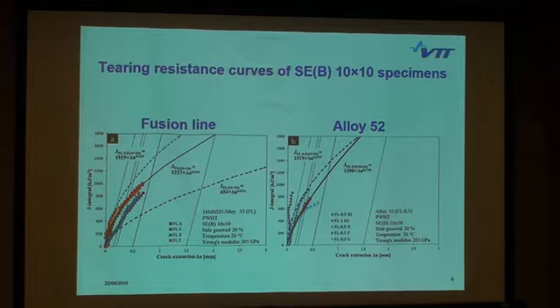And here it's also possible that there are some effects of crack location, of being exactly where it's nominally manufactured. And the scatter is also higher here than compared to the results that I showed for single edge bend 10 times 20 specimens.